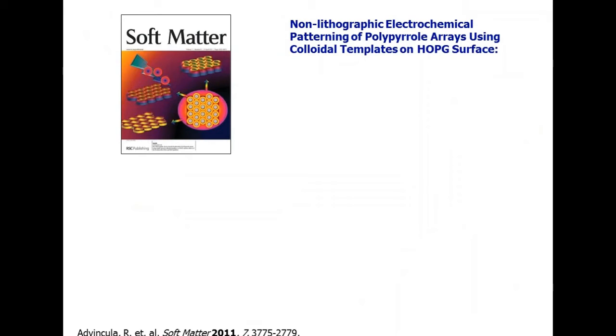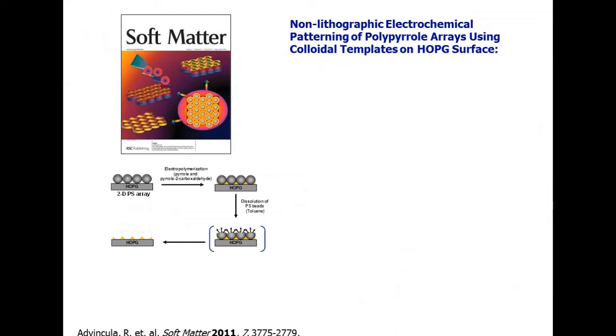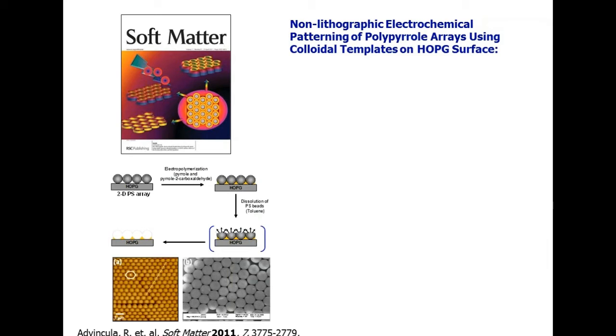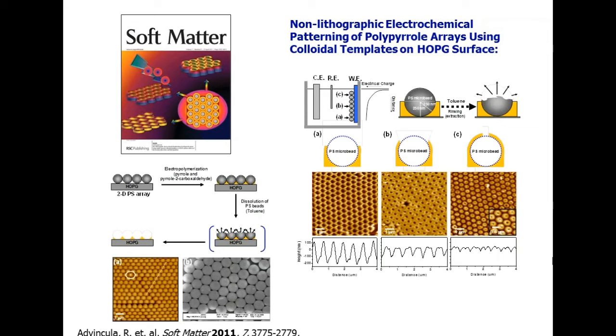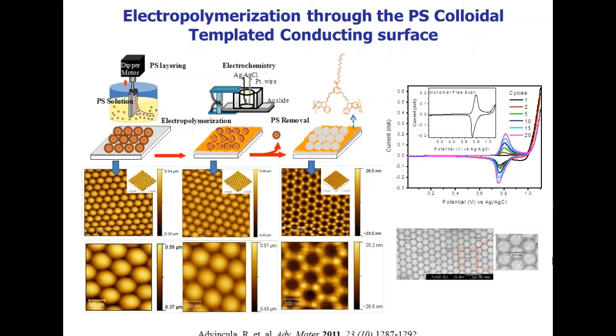So from molecular, we can go to micron sizes. In this case, we utilized a colloidal templating method based on particles that can be templated on a surface. This templated surface is made up of colloidal particles that are hexagonally packed on an electrode surface, and then polymerizing around this pattern so that you can get honeycomb, full dome, and half dome structures made of the original conducting polymer material. So we were successful in doing this and reporting the use of templating to produce these array films, where we have a conducting polymer array with holes being the exposed electrode surface.